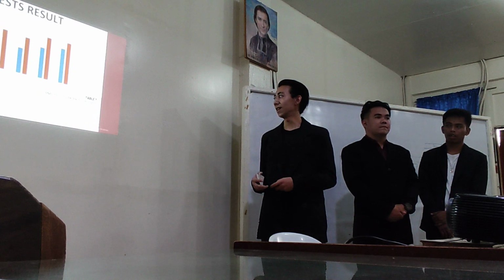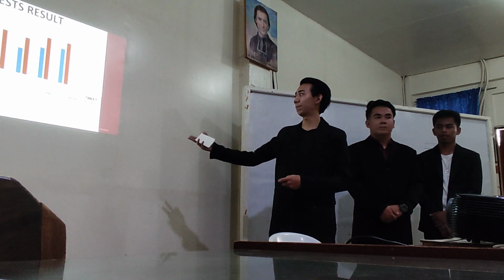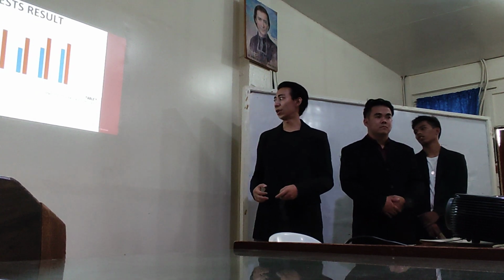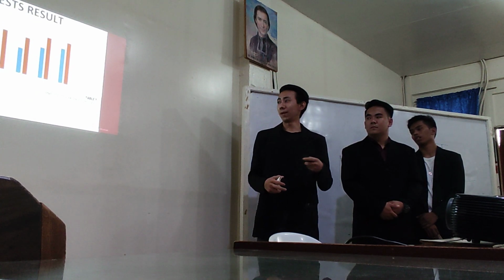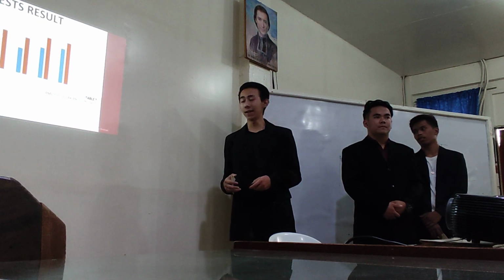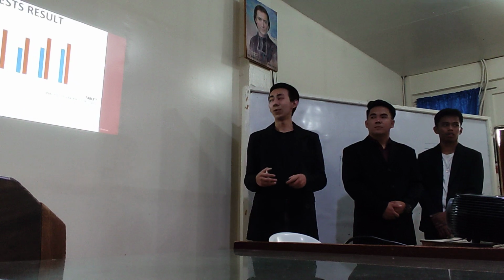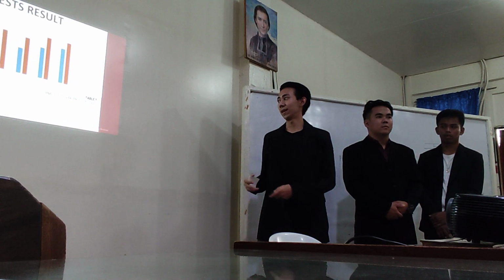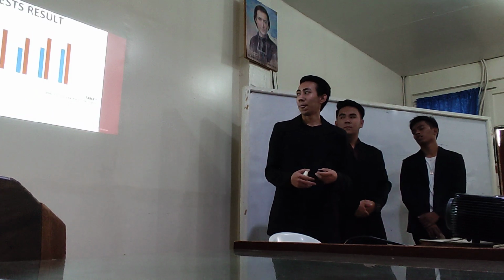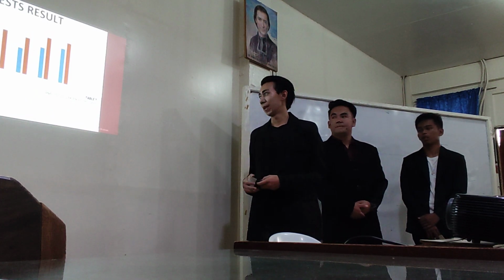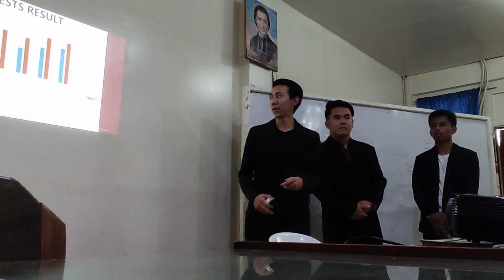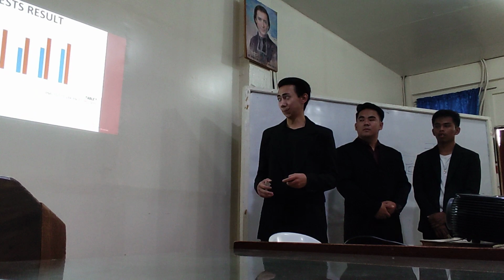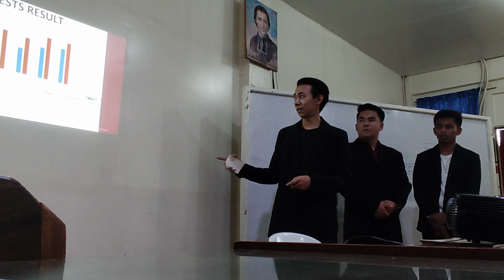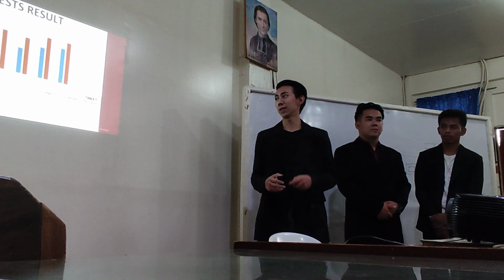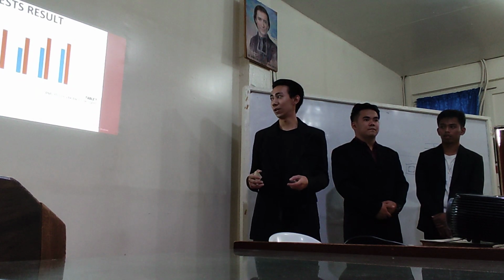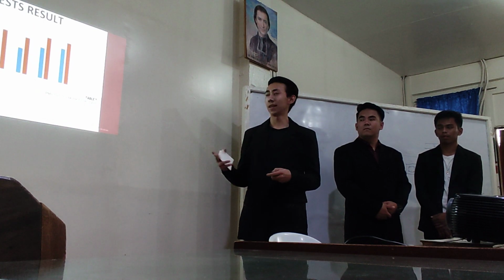This table shows the result for the 7 days. As you can see in the p-value column, it is less than the 0.05 alpha level, which means that we can reject the null hypothesis and accept the alternative hypothesis, which means that they have a significant difference. Now, let's proceed to the analysis of variance for 14 days. As you can see in the p-value column, it also is below the 0.05 alpha level, which means it has the same result as the 7 days: we can reject the null hypothesis and accept the alternative hypothesis, which means that each specimen has significant differences.